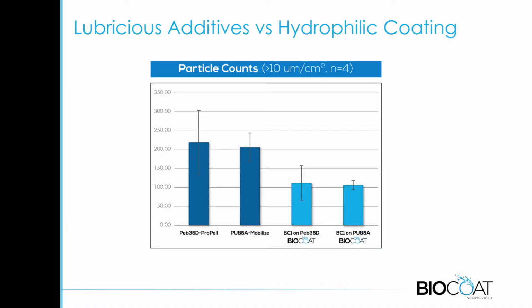So we want to look at the particulates of these devices or these tubings as well as compared to a hydrophilic coating. And in this case, let's start with the hydrophilic coatings. They have a total of greater than 10 micron particles of around 100 on these. And the ones with these additives, it's about twice that, around 200, which is not bad.